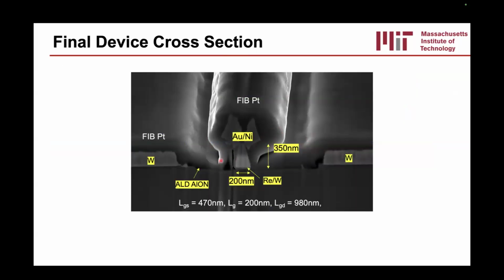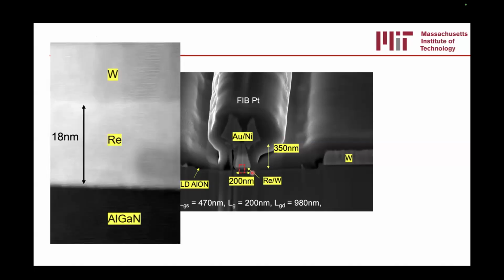They look something like this, where you can kind of see the tungsten ohmics, the T-gate nickel gold, and if you squint really hard, you can see the rhenium layer, rhenium tungsten right there. And this is a 200 nanometer gate length. If you do a STEM in this region, you can actually see that the rhenium looks really good. It's actually single crystalline to the AlGaN due to the sputtering process, and the tungsten is polycrystalline to the rhenium.